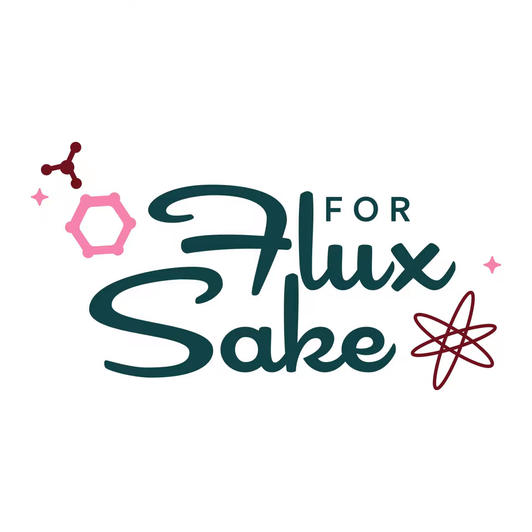There is definitely a defensive bentonite out in the world where a lot of people will put bentonite in every recipe because they think that they need it. And as you say, you don't. It's really not worth putting in there unless you know that that glaze is hard panning. Now, if it's the first time you mix up a glaze and you just go straight to batch, which don't do that, test it first, then you'll know if it's going to hard pan or not. But a lot of people will just cover their butts and put the bentonite in there when you don't need it. And then recipes get passed down and whatever. But as you say, if it's not hard panning, I wouldn't bother. So make sure it's hard panning first.